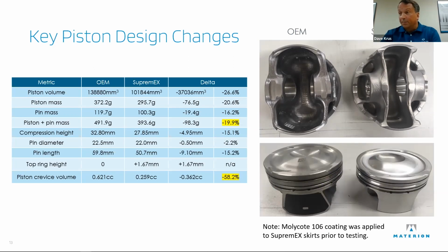And as I said, the pin was much shorter, but overall those two numbers in yellow on the table there, nearly 20% reduction in piston and pin mass with the shorter pin and the much lighter piston. And we forged the piston directly as much to shape as possible. MMCs are a little bit difficult to machine. So if you can save yourself some time hogging out the undercrown by machining or forging it to near net shape, that's always a good idea.